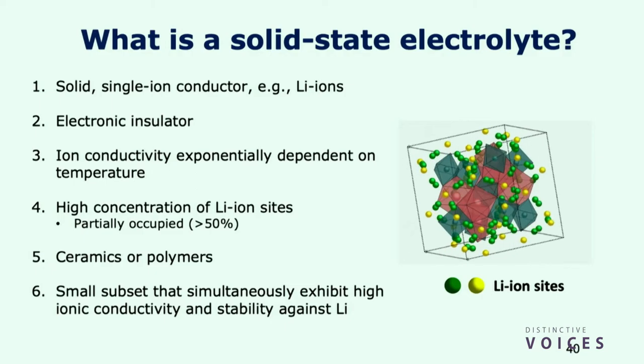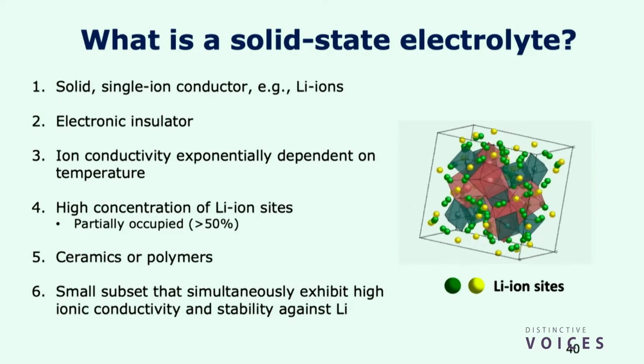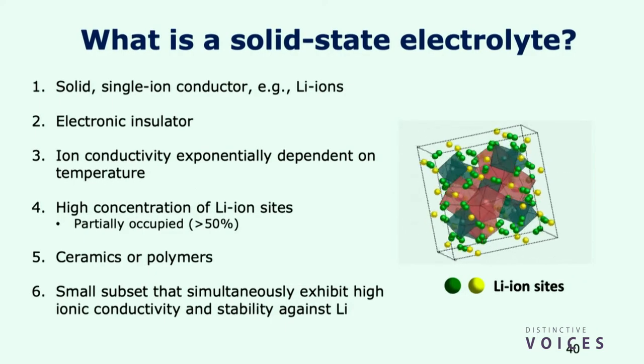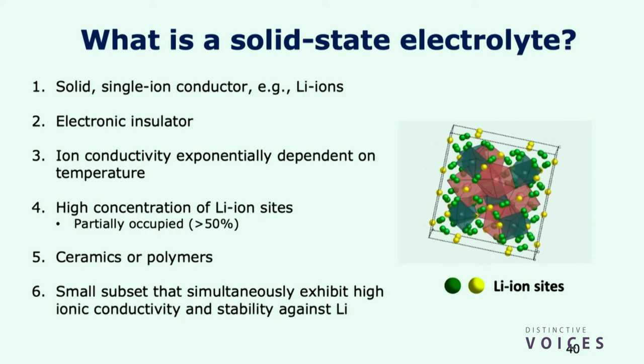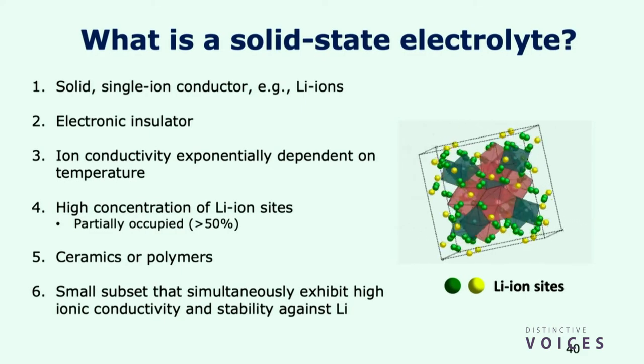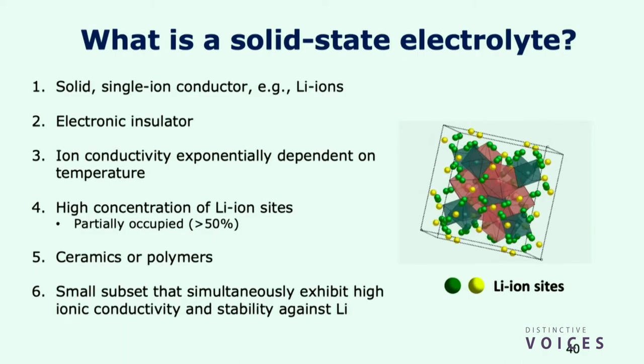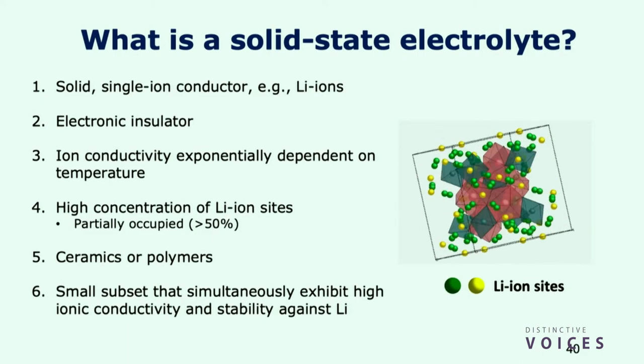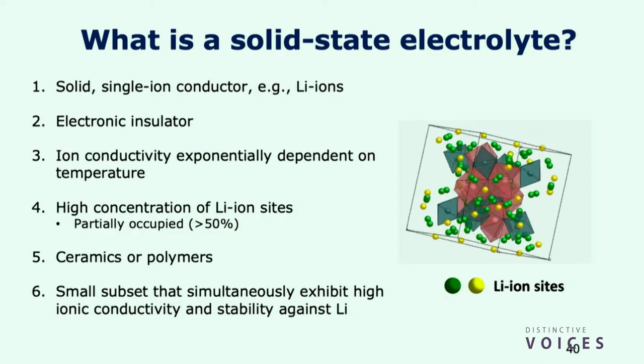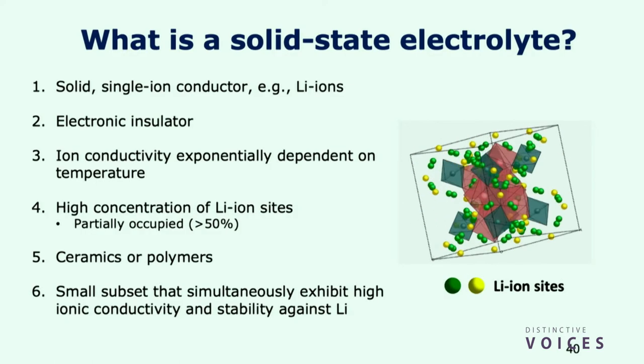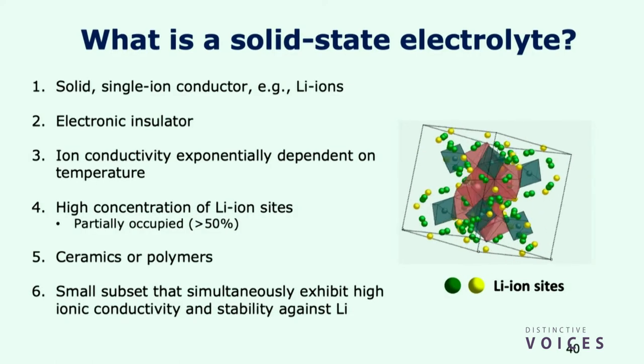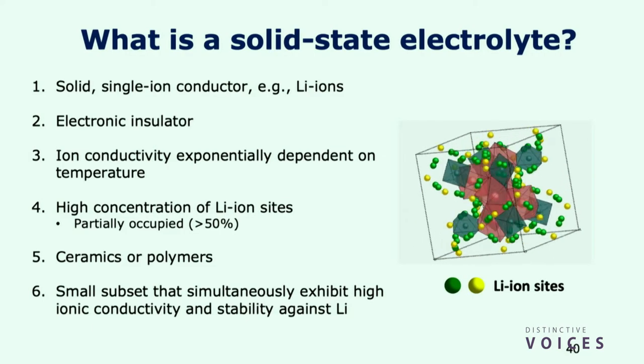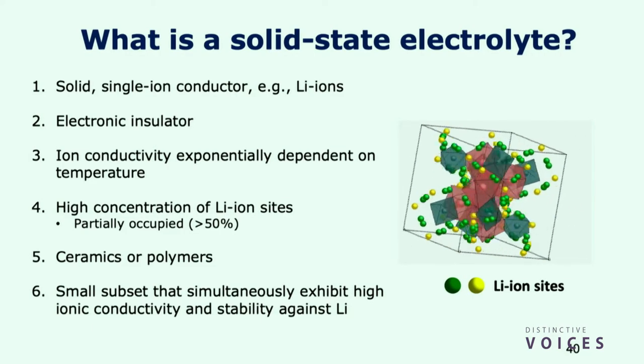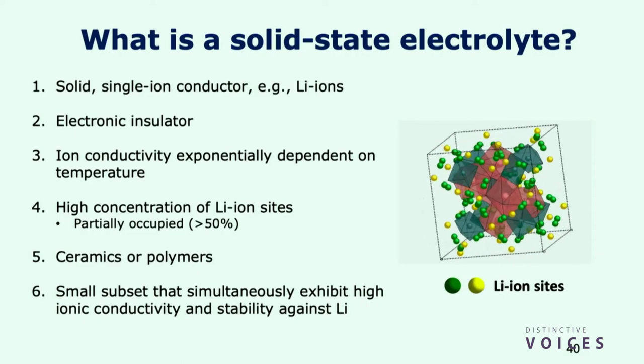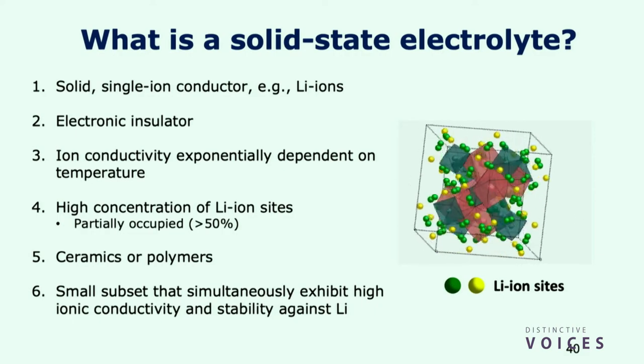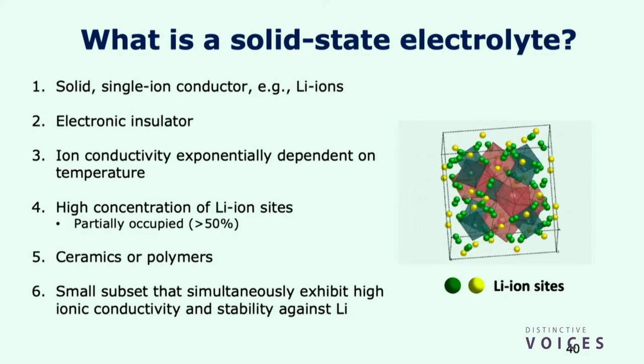What are these materials? These are typically crystalline ceramic materials. They conduct one ion, that's a lithium ion. They cannot conduct electrons, because then there'd be a short circuit. Like I said, the transport of ions typically increases exponentially with temperature. That's the nature of the transport mechanism. Most of that volume is occupied by lithium ions. There's ceramics, there's some polymers, but there are very few ceramics out there that conduct ions as fast as the liquid does at room temp and that are stable against metallic lithium.